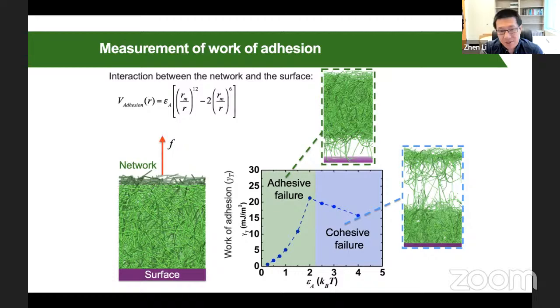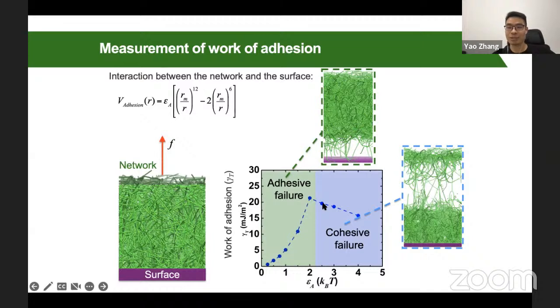So this means you can compute a density profile of the polymers, and maybe take 1% of the bulk density, and then you need to take some number to determine it, right? Yeah, that's good. You can see that I choose several points, and at least at these data points you can clearly see the difference. For example, at the highest point, you can see that it doesn't have failure within the network. But at the selected point, we can clearly see this cohesive failure. You can see that the network breaks into two parts.